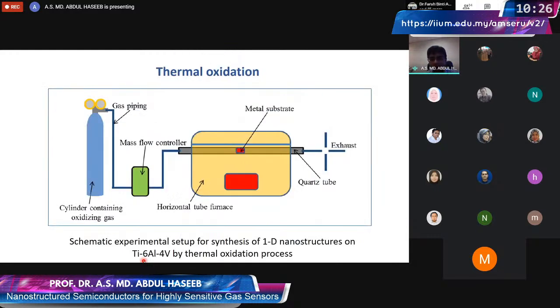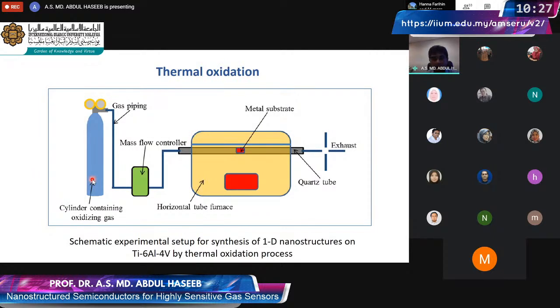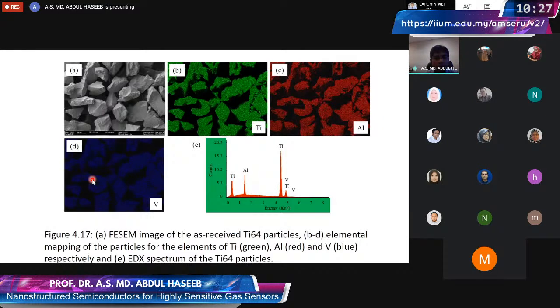And this is how we do it. We have a furnace where we control the temperature, we control the environment in a quartz tube, and we keep the sample inside. And by controlling the gas and other conditions, then we find a window of processing where we can grow nanostructures or one-dimensional nanostructures in an efficient way. And I will explain to you how we optimize them. So we started with this particle.